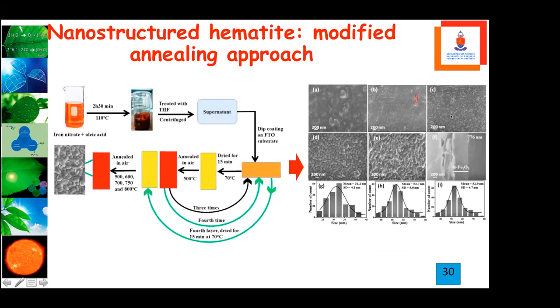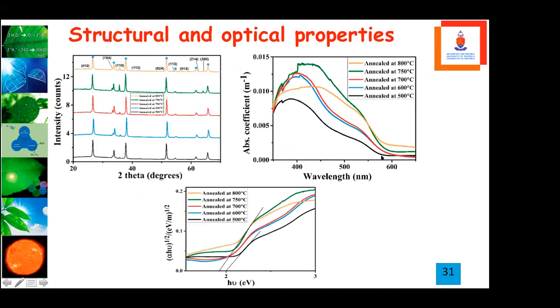The pictures here show that we are able to make nanostructures with very small diameters, like 31.2 nm, for this material, hematite. And then we did the annealing studies. In the annealing, as you see here, we used our normal XRD, and we would be very happy to go to a synchrotron facility and do these measurements again and see what we get with in situ measurements.